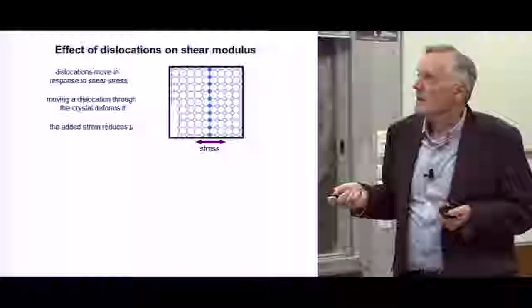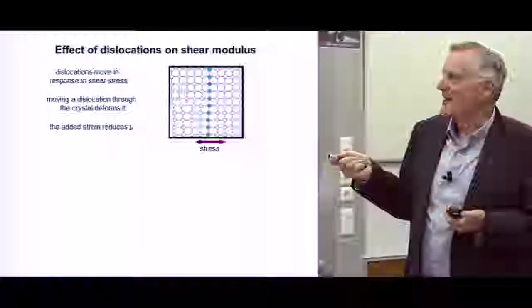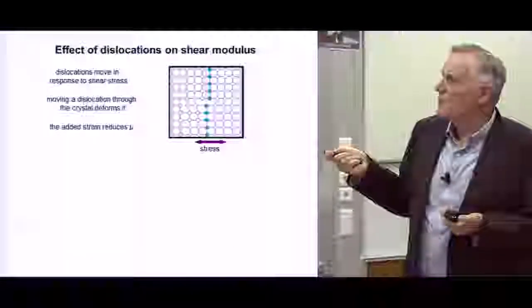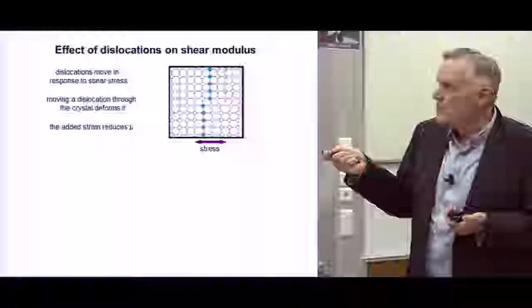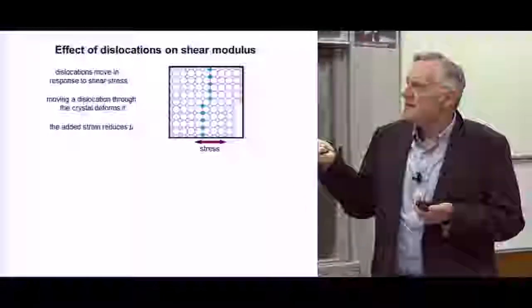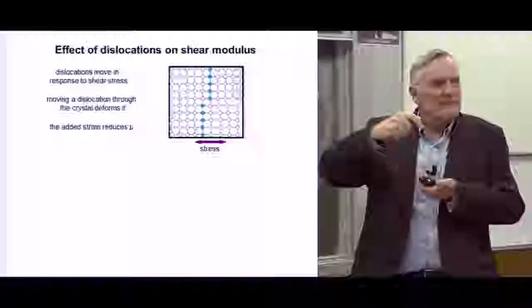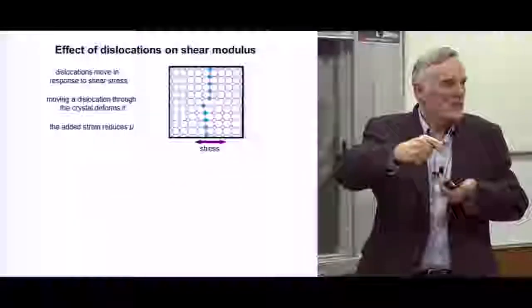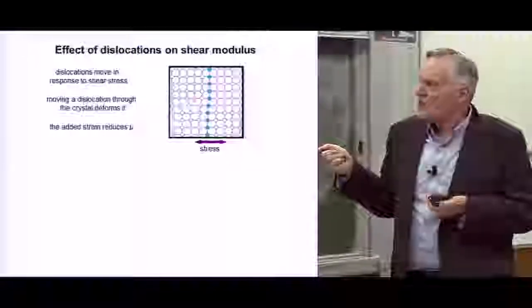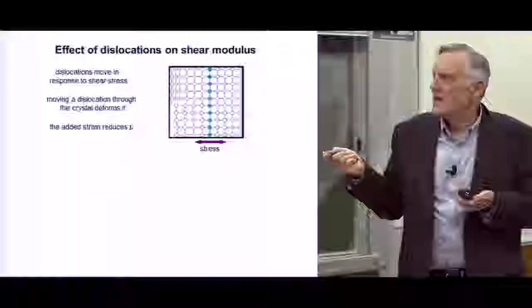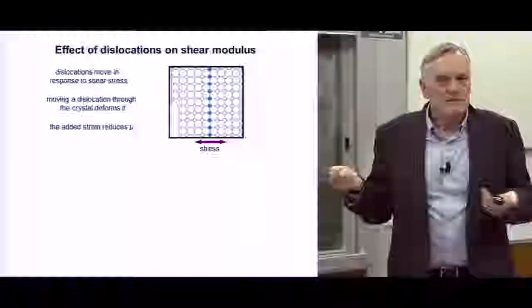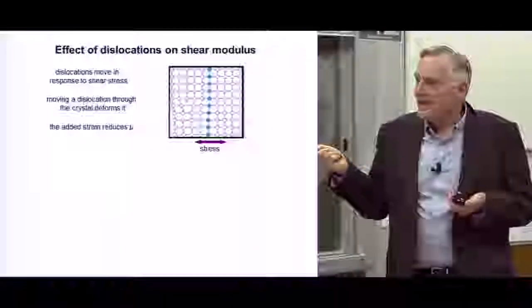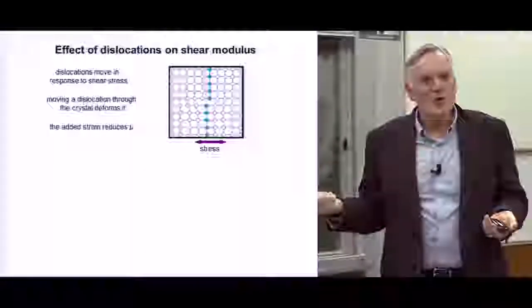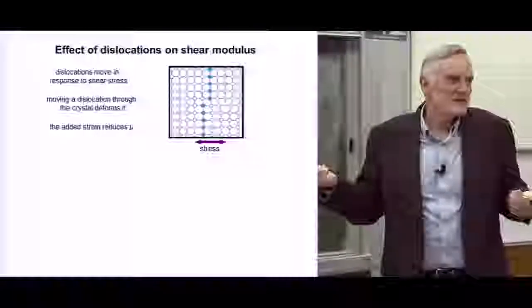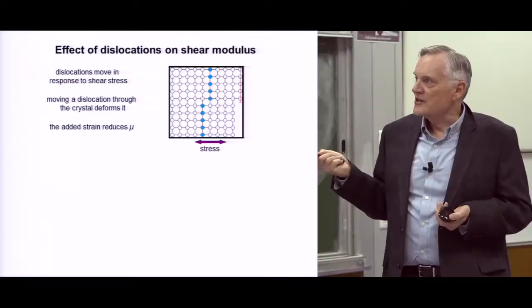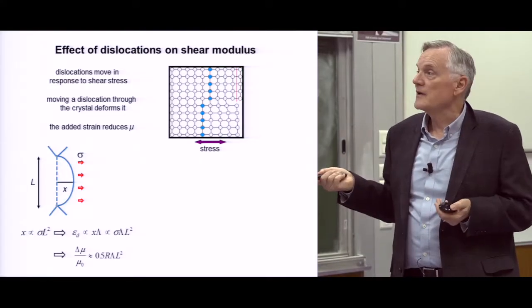Well, here's my student's simulation. The little red thing that's moving represents a dislocation, the edge of this, moving through a crystal. If it goes through once, you'll notice that it rearranges and shifts half of the crystal above it by a complete lattice spacing, one way or the other. So the dislocations move fairly easily because they're local deformations. But when they move right through, they cause a strain, an actual shear strain. And if you have the same force and more strain, that corresponds to a smaller shear modulus, basically. So they soften the shear modulus of the crystal if they can move through it.